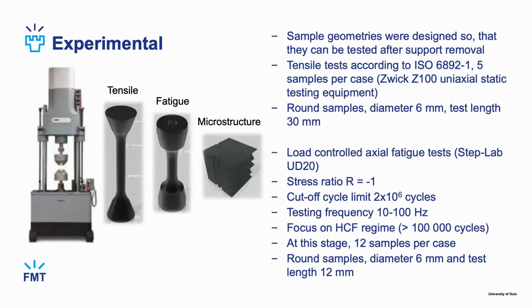The testing was done in a uniaxial way, so fatigue and tensile. The samples were designed so that we can test them in as-built condition if we want, so we don't need to do any prior machining. So we have these tensile, fatigue and microstructure samples. First, the tensile tests were done according to the ISO standard. We use round samples with a nice diameter and test length, so we don't have an increased necking effect.